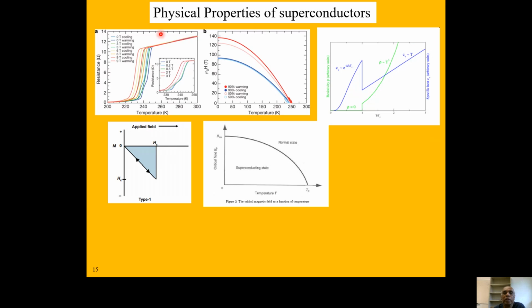So that's one physical property. The other one is, like I said, your resistance goes to zero at your TC value. You can see they don't just directly fall to zero, but if you do it at different magnetic fields, you can see then your TC becomes even lower. This is for zero field. If you go to very high, like 9 Tesla, you can see your TC becomes much lower. This is one of the high temperature superconductors.